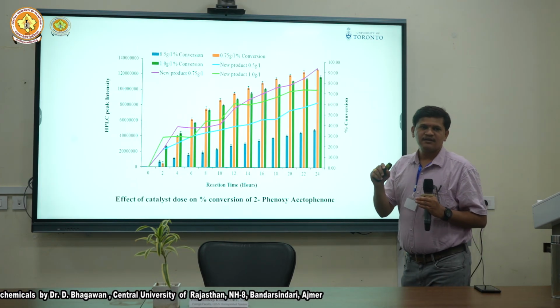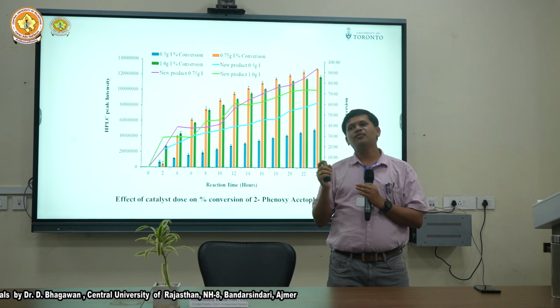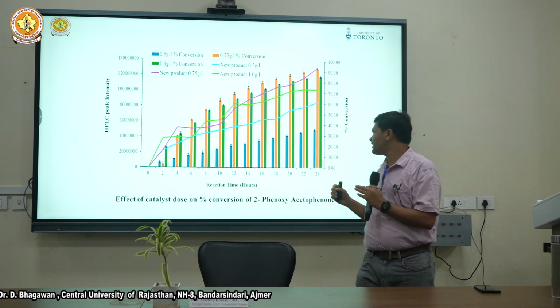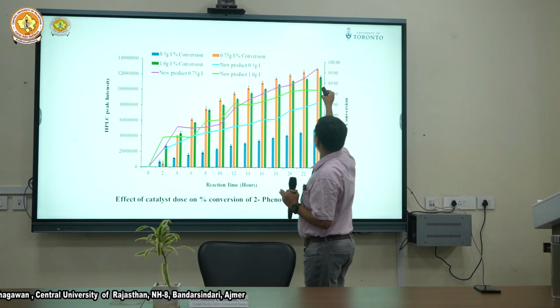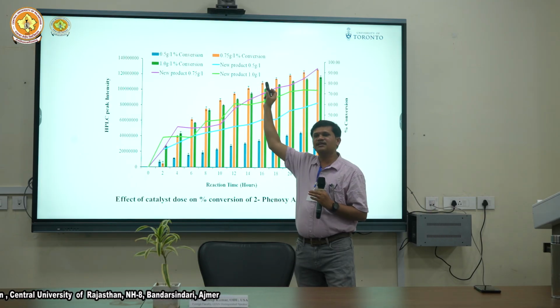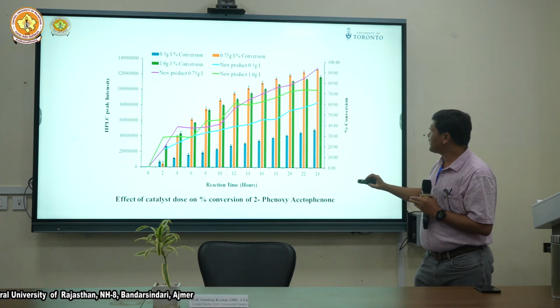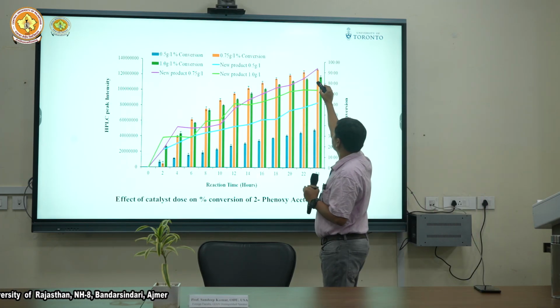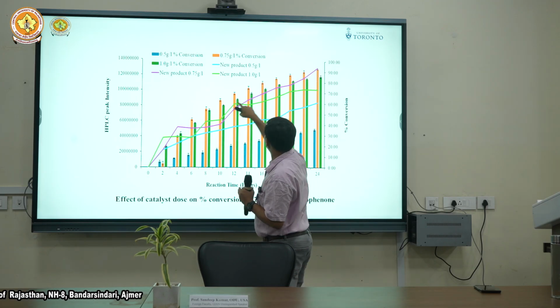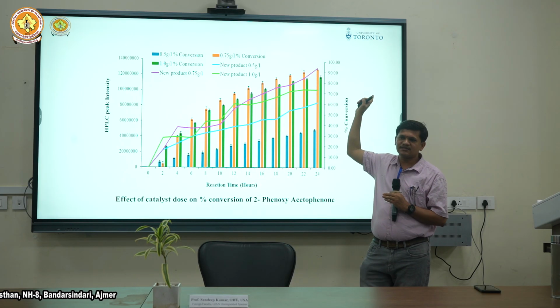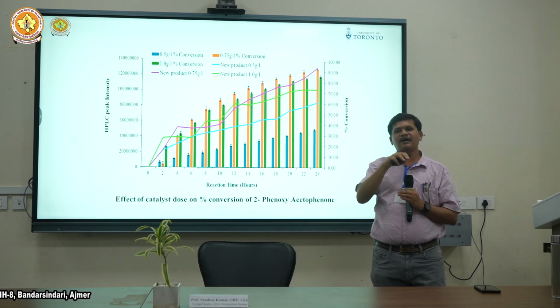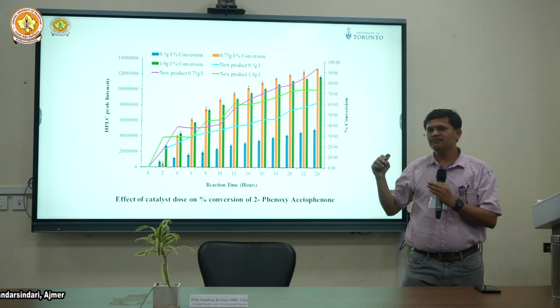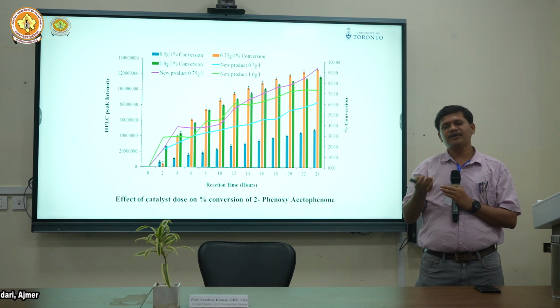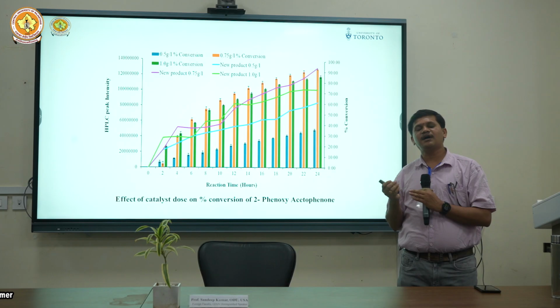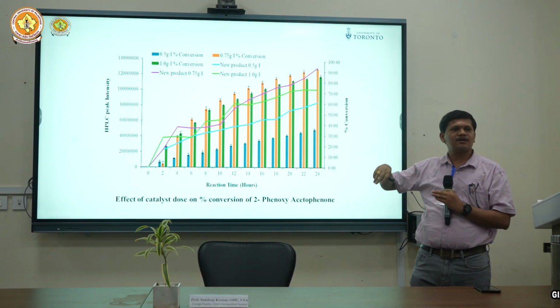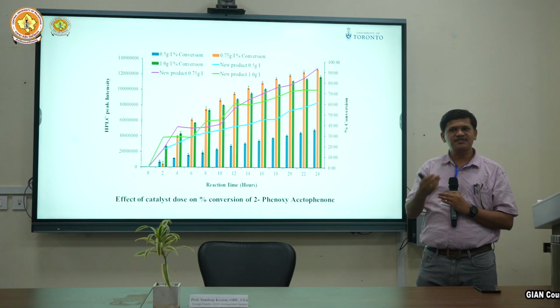And as I am mentioning, along with compound conversion, new compound formation concentration has also been identified. Here, if you see this orange peak, we have the highest conversion with a concentration of 0.75 gram per liter. And for compound formation, you can see this pink line. With increasing concentration, the compound concentration has also increased. Somehow here it has a different trend. It might be because of uninterrupted oxidation state, or maybe because of different other oxidizing radicals which are participating in the reaction.